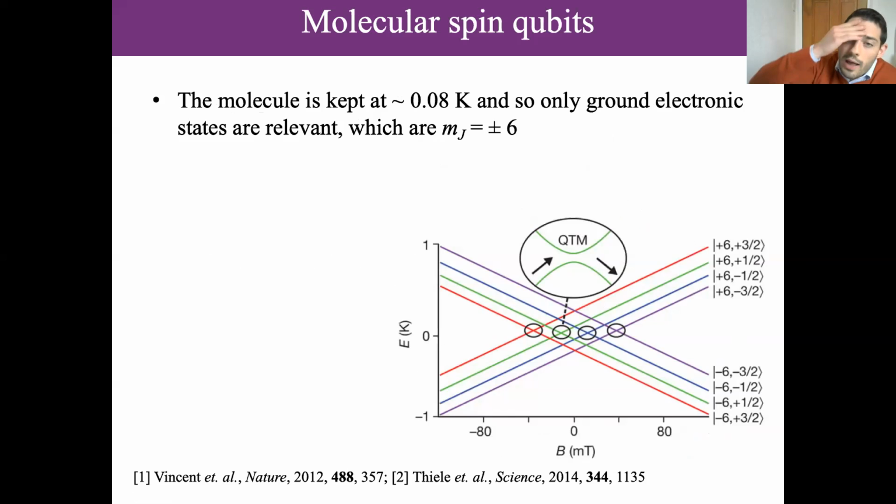And so what you have is essentially, you don't have a Kramers doublet. This is a non-Kramers system. It's J=6 for terbium-3+. So you have an MJ plus or minus 6 ground state that actually has some slight avoided crossing near zero field, being non-Kramers. And terbium has a 100% I=3/2 nuclear spin, so you have this kind of hyperfine pattern. There's also quadrupole splitting, which is known for this.